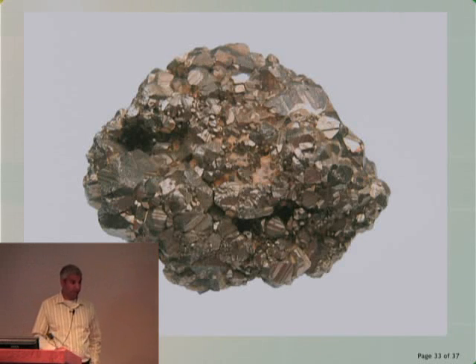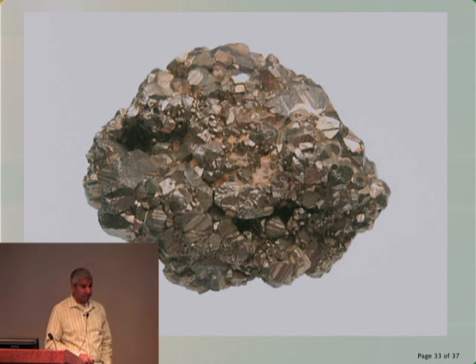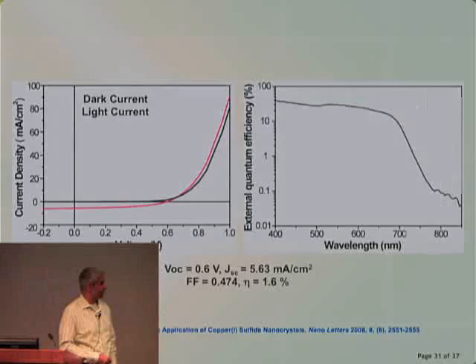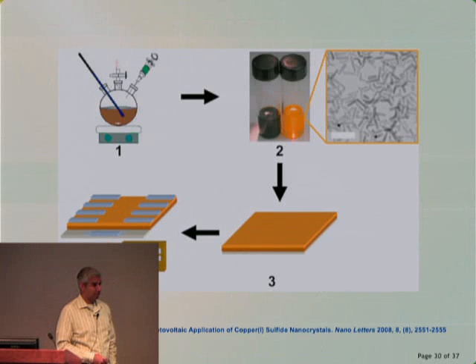Excuse me, you told us how you put down the copper sulfide, but where did the cadmium sulfide come in? So the cadmium sulfide is there to create the... No, I know that, but you have this procedure. Where is the cadmium sulfide in this procedure? We do another synthesis of cadmium sulfide, so separate, not shown, and then we clean it and we put it in vials like this, and then we use that after the copper sulfide is laid down, we deposit the cadmium sulfide on top of that. So it's a sequential deposition.